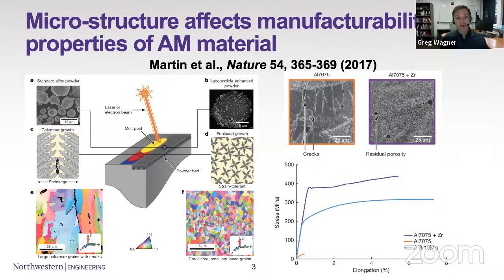And it can affect not just properties, but even whether or not a particular material can be built, right? So we know that there are materials like aluminum that don't lend themselves very well to additive manufacturing. Typically, these are the same materials that don't lend themselves to welding, and a lot of times it's because they have phenomena like hot cracking. So this paper from a few years ago in Nature demonstrated that this aluminum, a 7000 series aluminum, under standard conditions in additive manufacturing developed cracks, and here's the resulting stress strain curve. Essentially they couldn't get a coherent material that could bear a load.